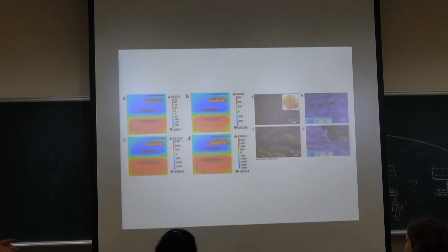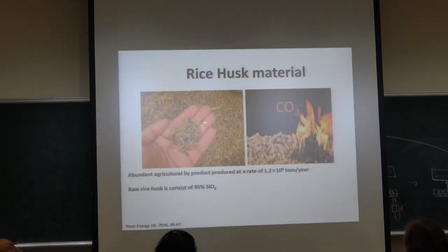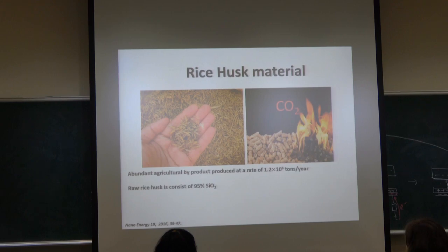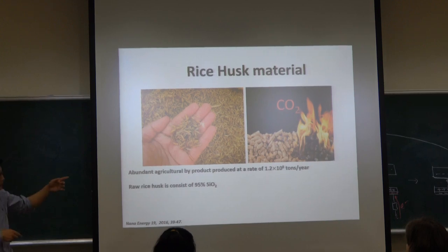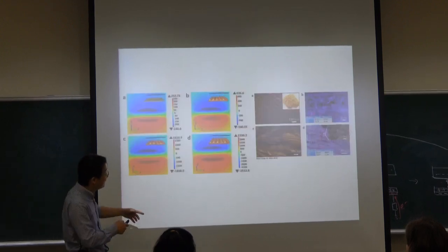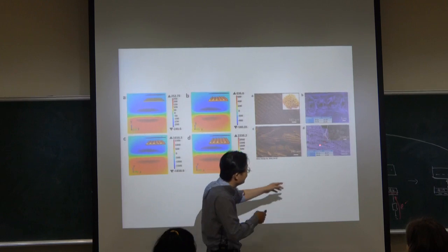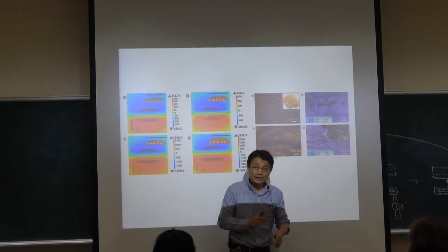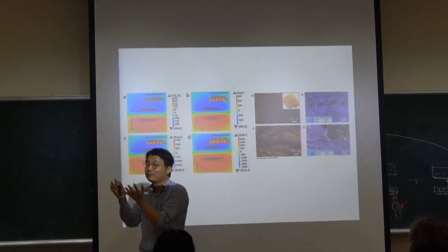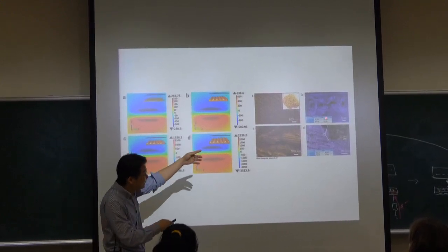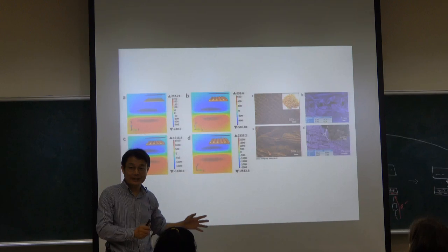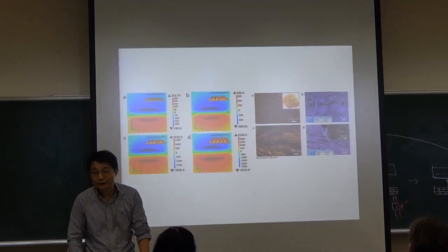But very interesting here is the rice husk. It has a 95% ingredient composition of SiO2, right? For the rice husk, as we can see, this is an SEM image. The cross-section image looks porous, right? It is porous. But of course, inside the rice husk there is cellulose.